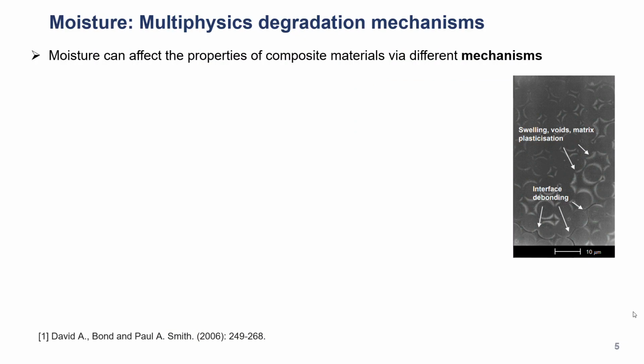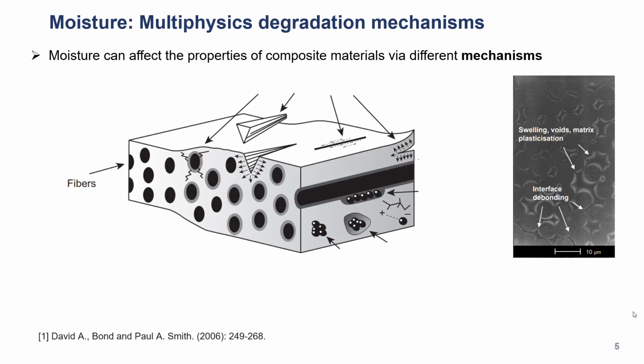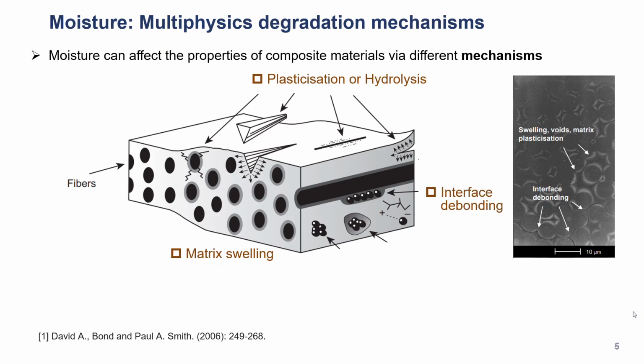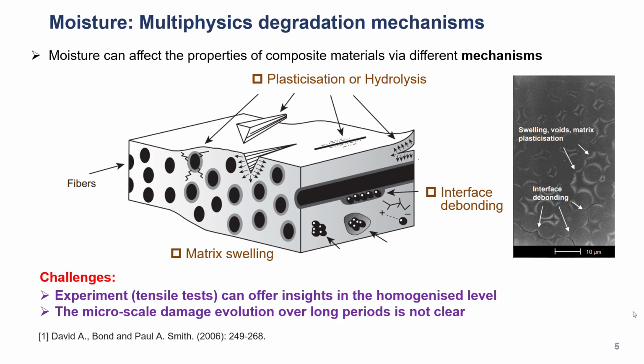From the experimental observations, we can hypothesize that moisture can cause the swelling of the matrix. It can also lead to matrix plasticization and hydrolysis. This could also introduce some fiber-matrix debonding. The challenge here is that current experimental results typically can only offer insight at the homogenized level. If we want to track the microscale damage initiation and evolution, this is super challenging.